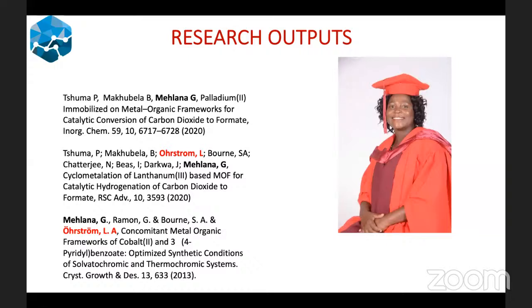Thank you. That's a very intelligent question, I must say. Of course, what you have proposed is very much possible. But from the studies that we did, we looked at the ruthenium p-cymene complex on its own. It's a dimer. Under homogeneous conditions, just to check, we realized that it was active, giving a yield of about 24%. But once this is grafted into the MOF, we saw a significant increase in the amount of formate that was formed, and we attribute that to the ruthenium-2 that was grafted to the MOF.